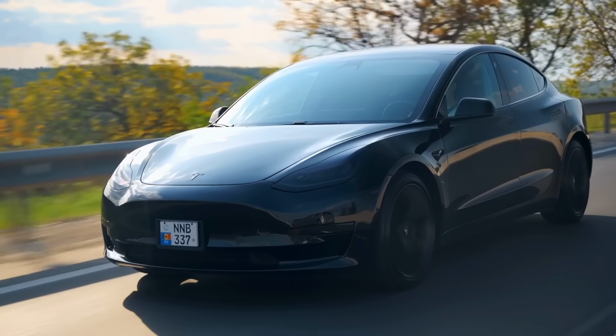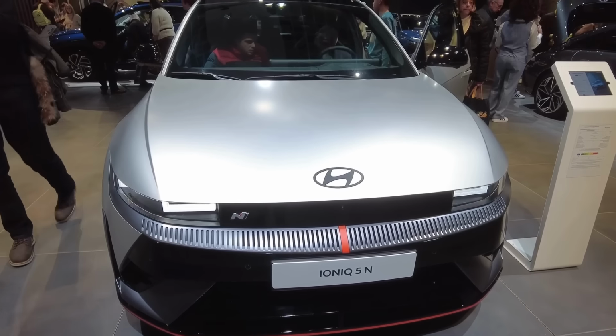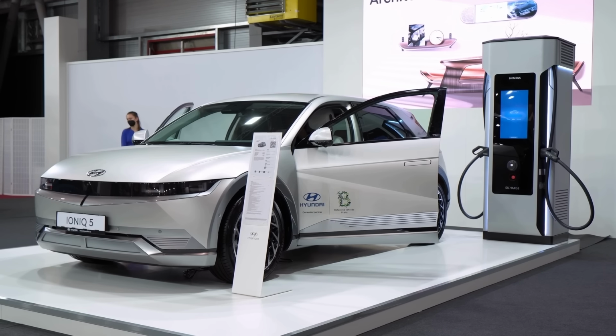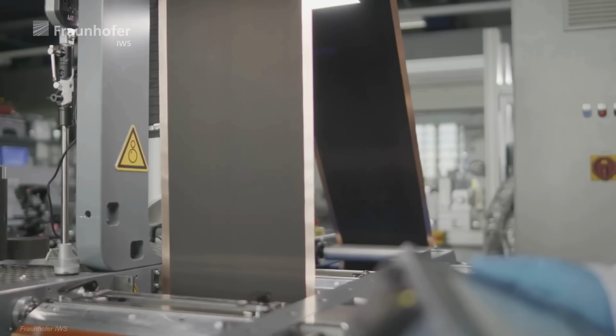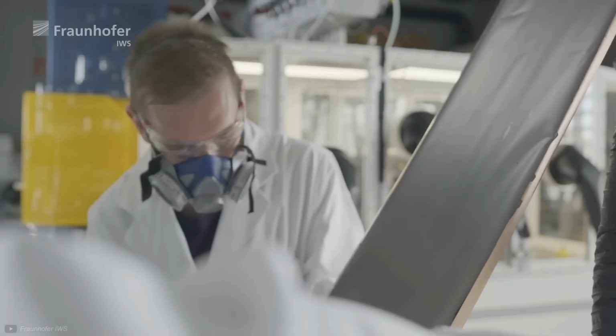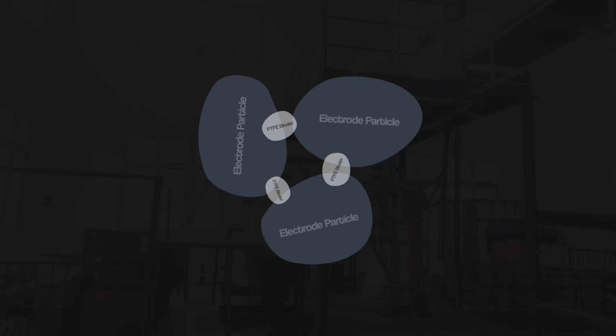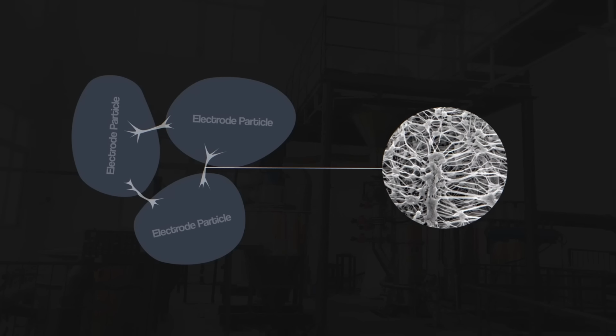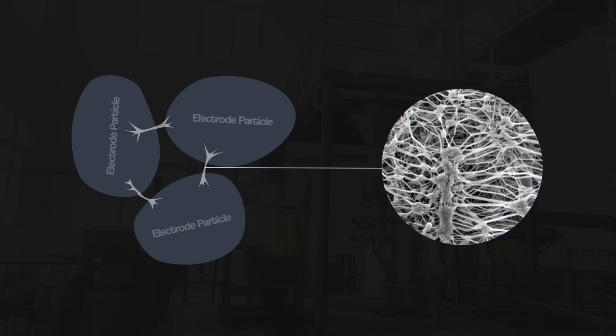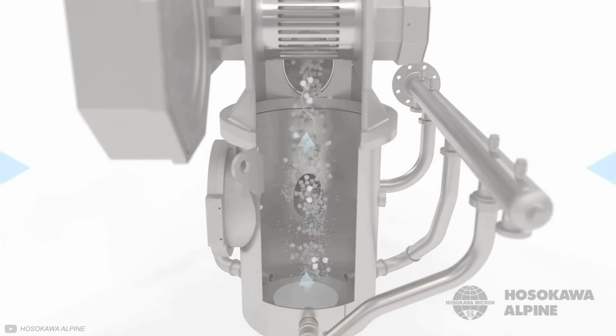My guess is that Tesla and their competitors have been holding out until they understood the process for cathodes too, and that's exactly what happened in the last few years. A lot of the unwanted side reactions in the cathode that had previously prevented the technology from scaling up seem to be due to it reacting with the binder material, which you'll remember is PTFE, which is turned into those sticky fibers that hold everything together after being exposed to a shear force.